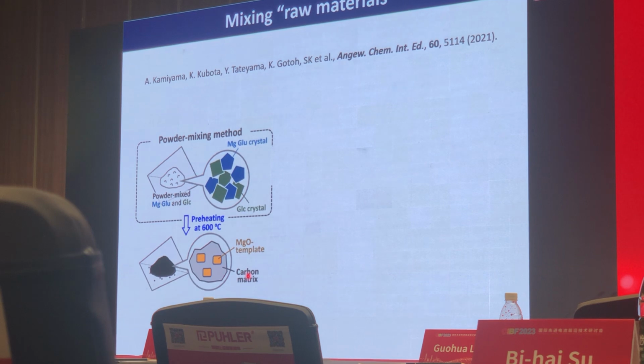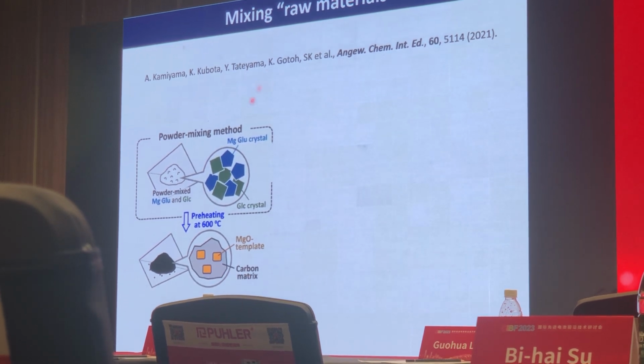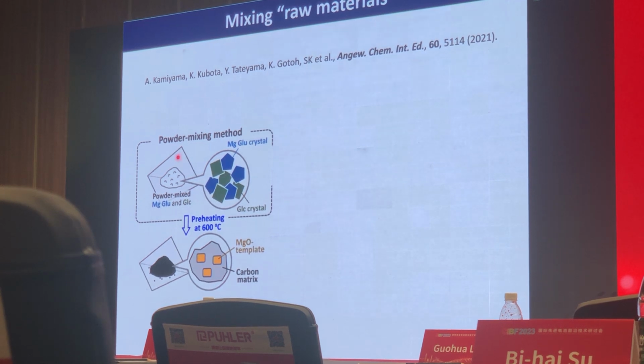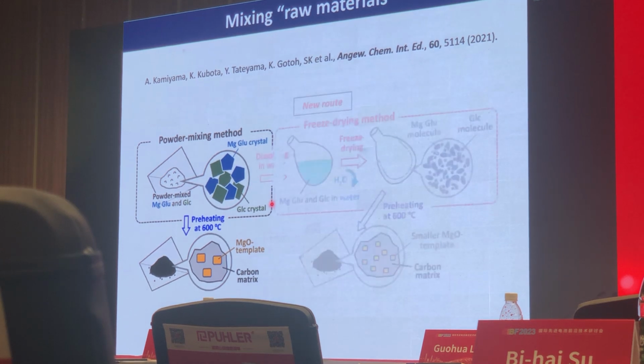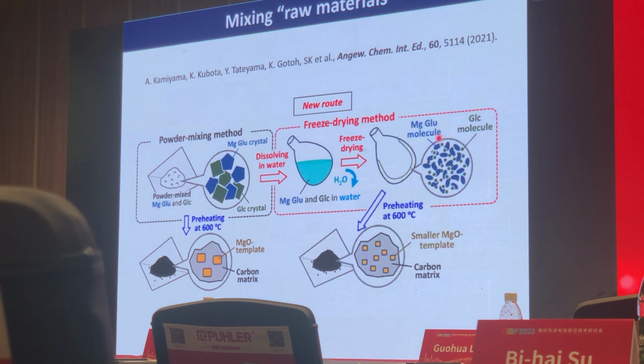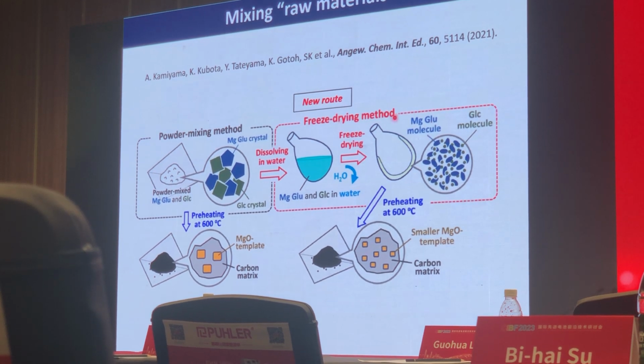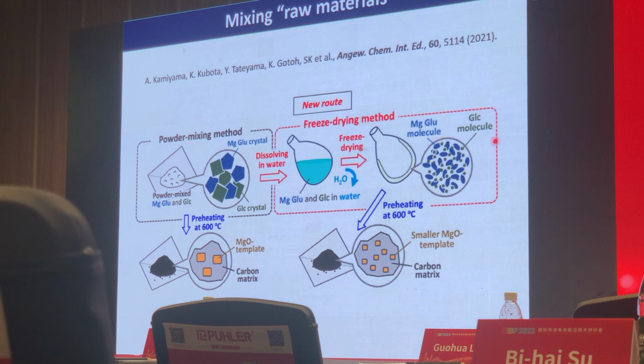So how do we synthesize the template material? The key point is how to mix raw materials. The conventional technique was powder mixing of magnesium gluconate and glucose, which are the starting materials for hard carbon. Our new synthetic route is based on freeze drying. First we dissolve the magnesium gluconate and glucose in water. Then to maintain an atomically homogeneous mixture, we treated it by freeze drying process. Then we have a very homogeneously mixed precursor. Then we carried out calcination, that is carbonization, of these starting materials.